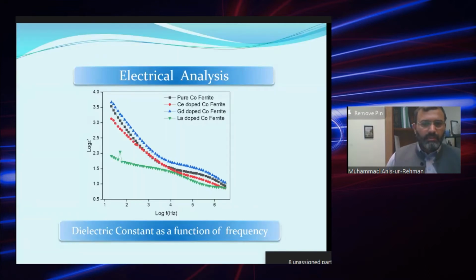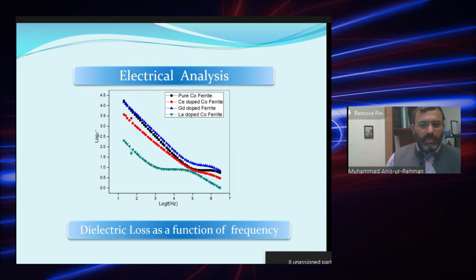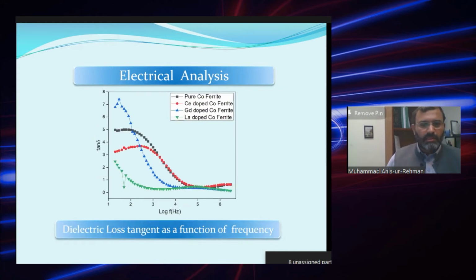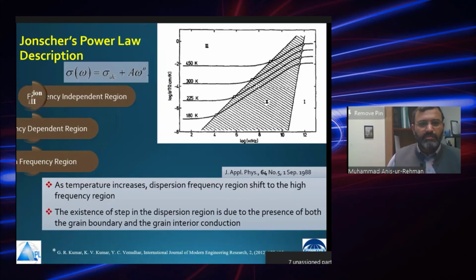Similar trend as we have seen in the last slide, that as we are increasing the frequency, the dielectric constant of the material is decreasing. We are getting good dielectric constant in the case of the gadolinium doped ferrite, and in the case of the lanthanum doped ferrites, the dielectric constant was not that good. The dielectric loss was also less in the lanthanum doped samples, and in the case of the tan delta, that is the energy losses, we are having two humps here that indicate that there are two polarization mechanisms which are dying out in this frequency range.